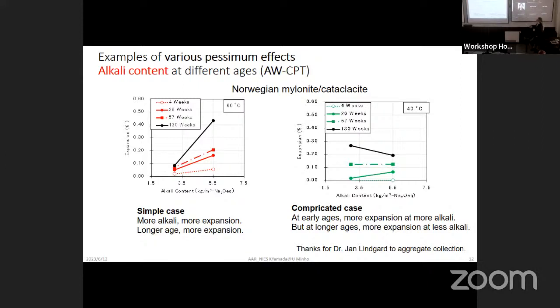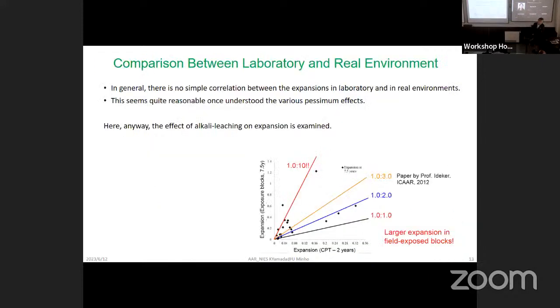At 40, as time passes, for more than 2 years or 3 years, less alkali expanded more. Then, in such a case, we cannot determine a threshold value. Of course, as I said, many engineers want to find some good method that can reproduce the expansion in the field by some laboratory test. That's a very terrible result. In general, we can only see.